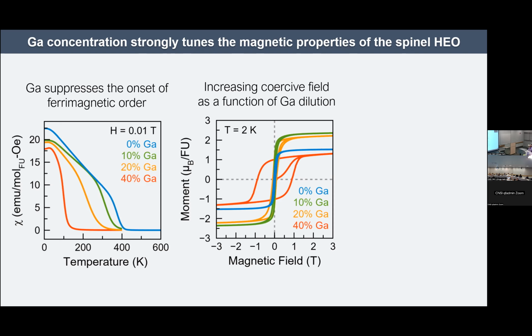So again, our 0% reference compound is 0% gallium here in blue. And when we begin to add in our non-magnetic ions, the first thing that happens is that the saturated moment actually goes up. So we have a larger saturated moment for these 10 and 20% gallium samples. And it's only when we've replaced nearly half of all of the atoms in our structure with something that's non-magnetic that we actually see a suppression of the saturated moment. And then the second thing you might observe is that the coercivity dramatically increases as we go from 20 to 40%. We see an order of magnitude increase in the hardness of the magnetic order.